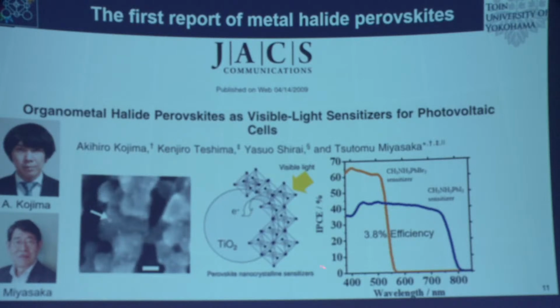This is the first report of using these metal halide perovskites in a solar cell. It was done by some colleagues from Toin University, Yokohama, Tom Miyasaka and his postdoc, Akihiro Kojima. They took this porous TiO2, and instead of using a dye, they coated it in small little nanocrystals of this perovskite. That was published in 2009.